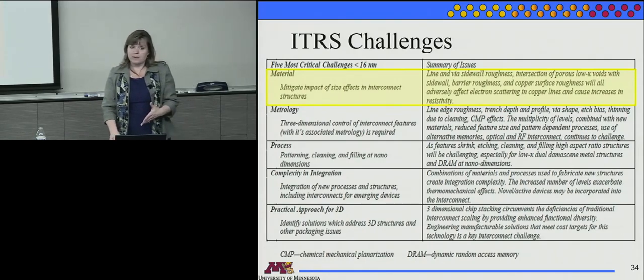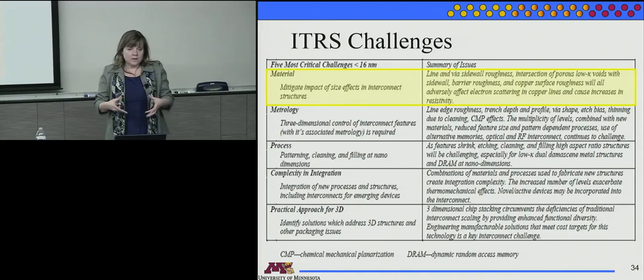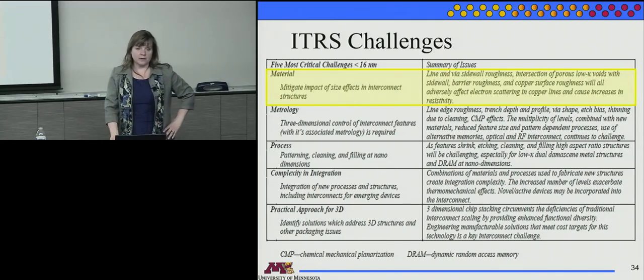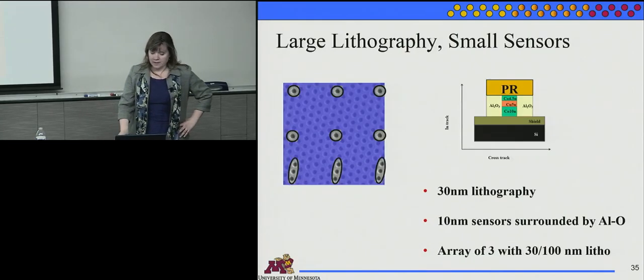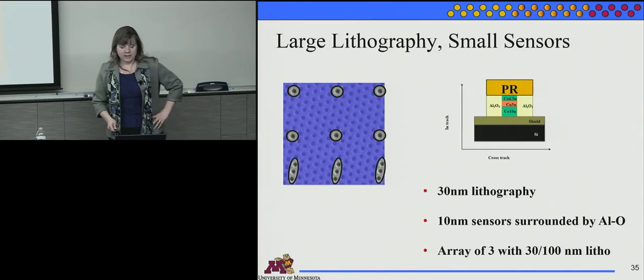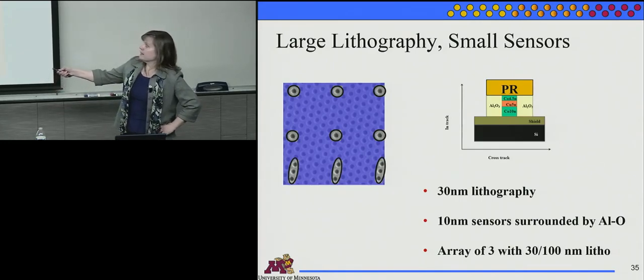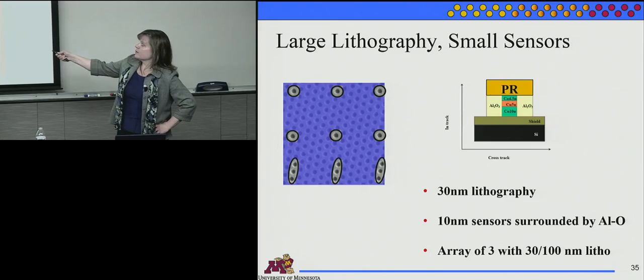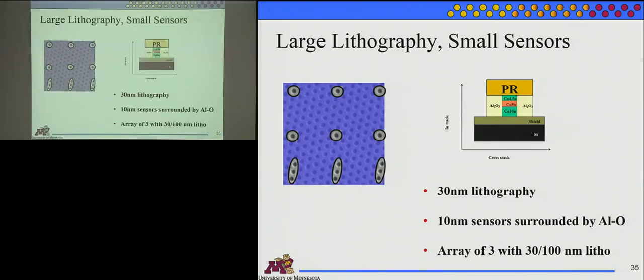Maybe we're going to see aluminum oxide even just because you could fill your via and have sidewalls that are perfectly smooth. We'll see. But that was another thing that made it interesting. And here's where the read heads come in again. Here's our aluminum oxide, which would be the first thing you'd want to do if you were processing these as a read head. We can go ahead and let them pattern a 30 nanometer dot. If they try to pattern the layers that I showed you, the Heusler alloys, smaller than 30, then the sidewall damage is so bad they don't even get an MR.